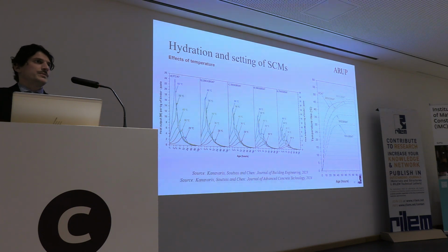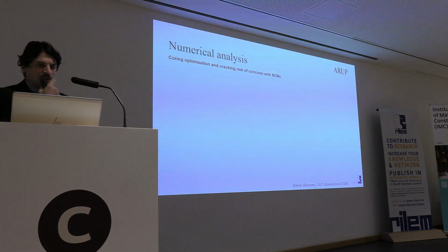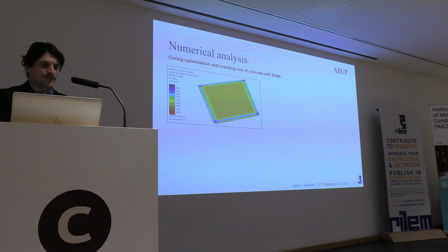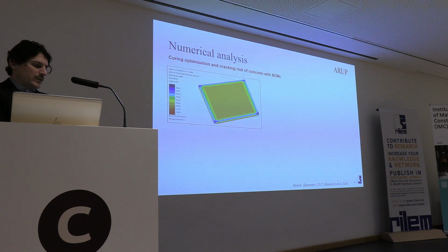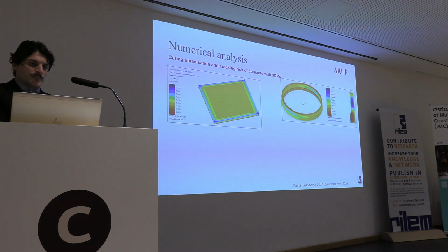Okay, we know it reduces the temperature, but also it reduces the tensile strain capacity. So in terms of controlling thermal cracking, there was a bit of debate at the time, and we were able to shed some light on that. So ultimately, we use this data to construct numerical models. For example, curing optimization of precast concrete elements in terms of what is the temperature regime that is required, and what is the maximum percentage of supplementary cementitious material that can be used without compromising the schedule of production, but also to construct thermomechanical analysis models for predicting thermal cracking in